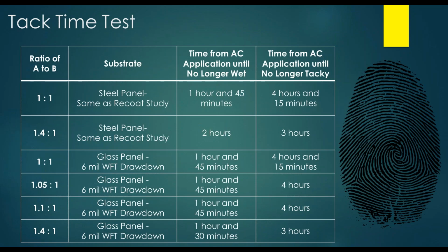The coating interval study was followed by a tack time test. And tack time is defined as the curing or drying period at which application of finger pressure on the coating results in only a slight impression without any removal of the coating on the finger, meaning it's basically the time in which the coating is no longer wet, but you can still see the effect of a slight finger pressure.